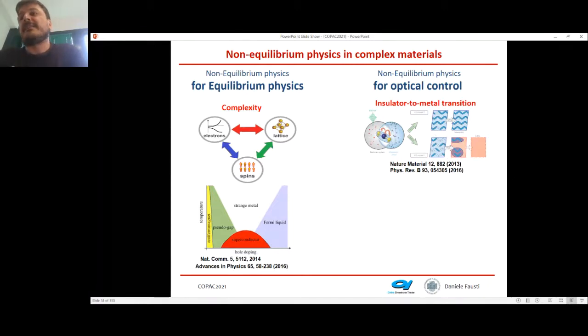This is a relatively trivial example in the sense that you do photoexcitation, and the photoexcitation results in a highly disordered state, which is the metallic state. And this is exactly what would happen if you just turn on the temperature. So if you just give disorder to the system. On the other hand, with the electric field, you can do something else.